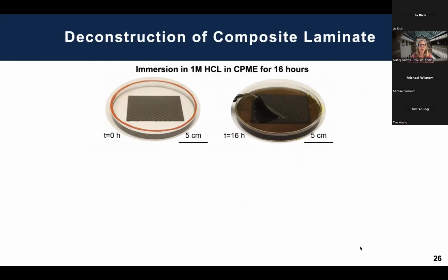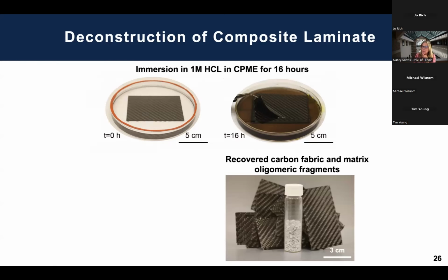So this is immersion. This is basically the hydrolysis process. We're taking 1 molar of HCl in CPME, and we basically take the whole composite, soak it, and then what's interesting, I love this image, is that you can just start to see the fibers can come out whole and undamaged. And basically we can recover the carbon fabric, which was a discussion in the prior talk. And we can grab out the oligomeric fragments from the solution after this is done.